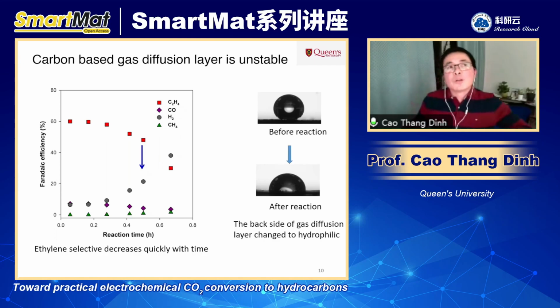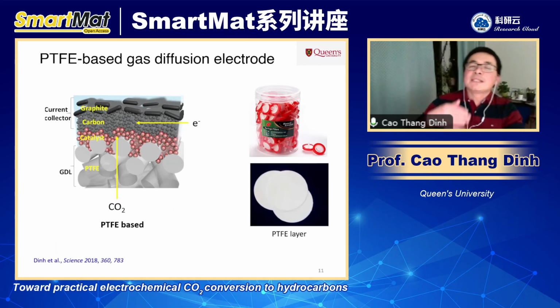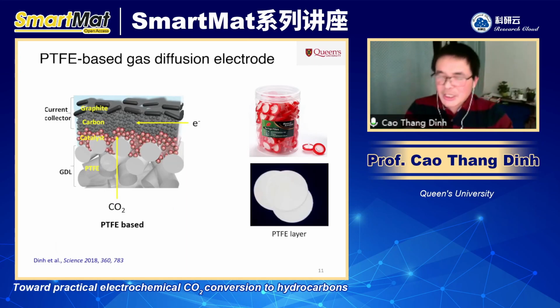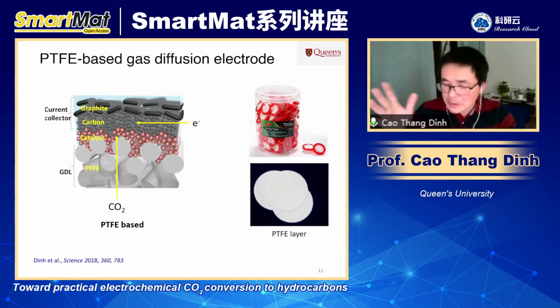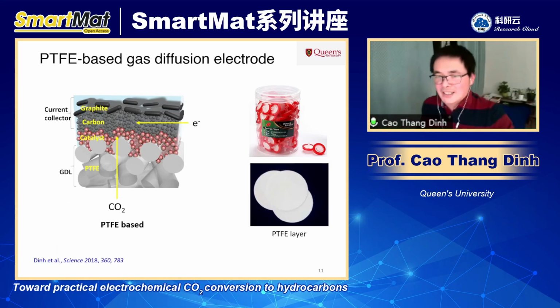So by that time, we came up with the idea: why should we use the carbon gas diffusion layer, and can we use something more stable? So I looked at different types of porous substrates that can be used for a gas diffusion layer. And I found this, on the right-hand side here, you can see a bunch of filters. It's basically a filter for non-polar solvent, so it must be hydrophobic, right? I cut all of the plastic outside, and then you have the small filter inside, and then we deposit the catalyst on top of that.